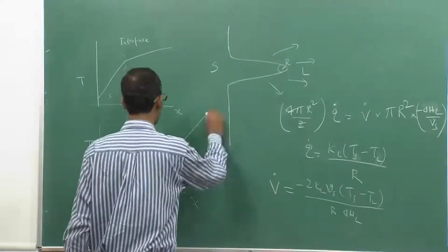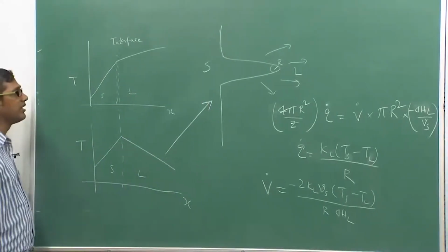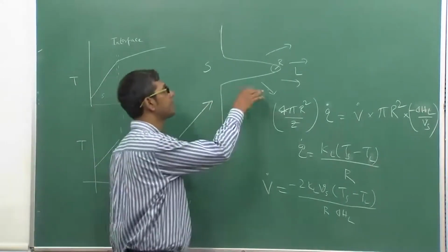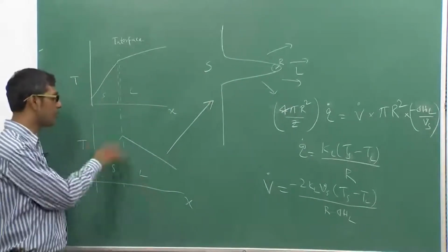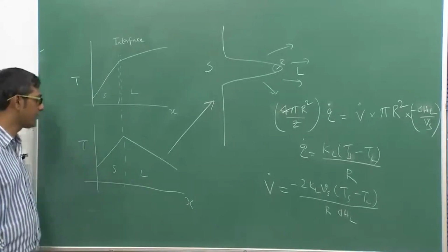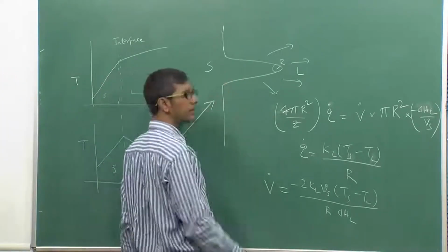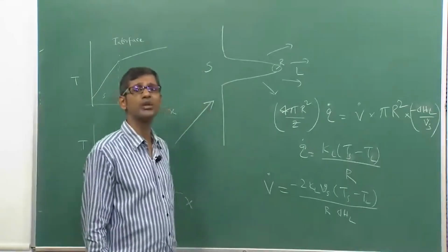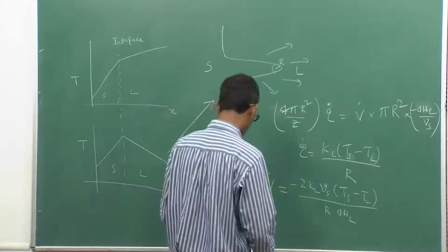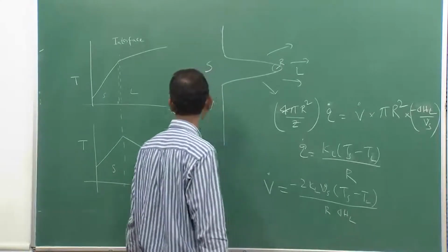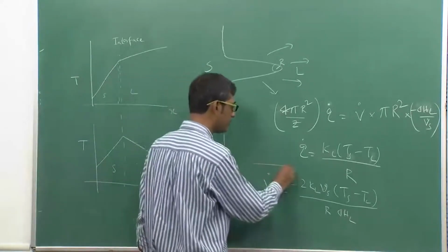This situation is similar to this. So the liquid has a negative temperature gradient. So heat will be basically rejected at the interface and transported into the liquid because of this negative temperature gradient developed. Okay, heat can also be transported to the solid, but transport to the liquid is faster than to the solid. That is what happens. Okay, and so this is the kind of calculation one can do.